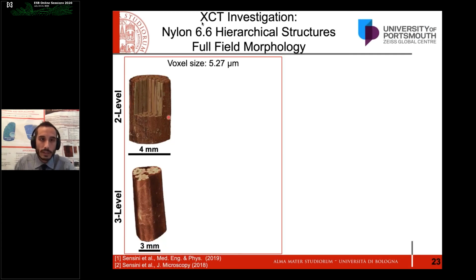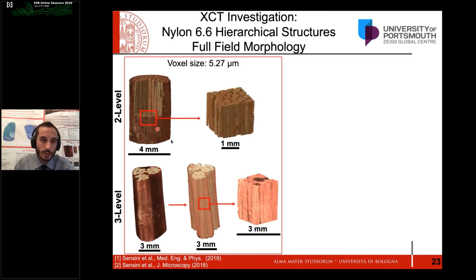We also investigated the two-level and three-level structures of nylon 6/6. Here you can see that the bundles inside, for both structures, result axially aligned and strongly grouped together. The electrospun membranes resulted homogeneous, and even in the internal volume of the structures, the hierarchical structures in the three-level scaffold resulted actually aligned.